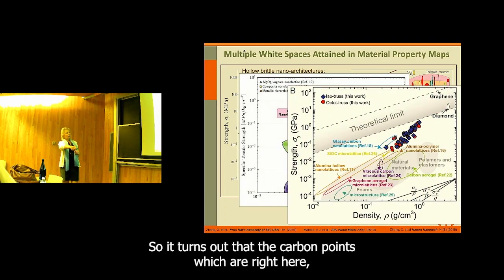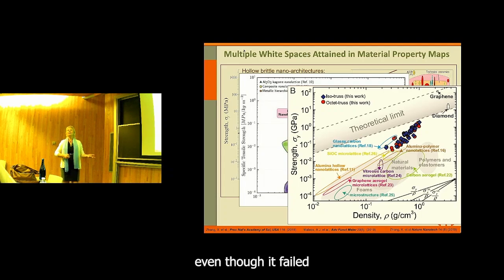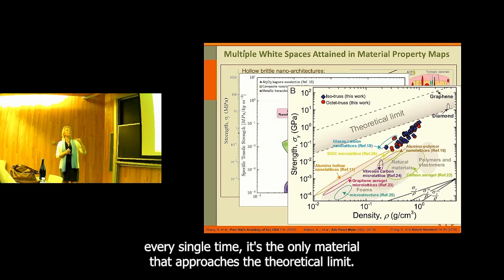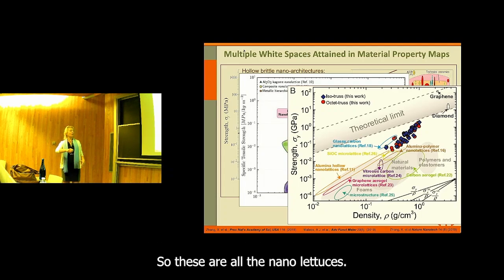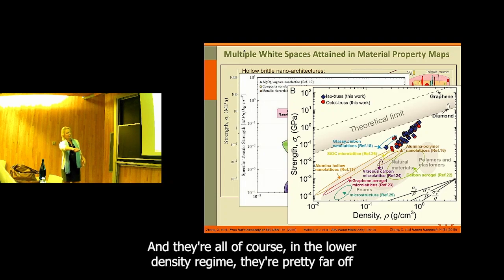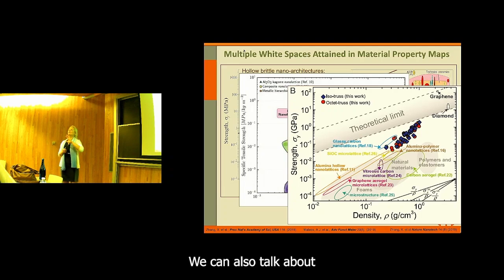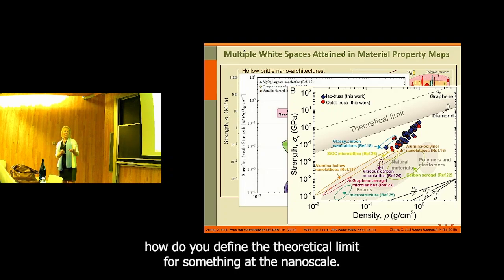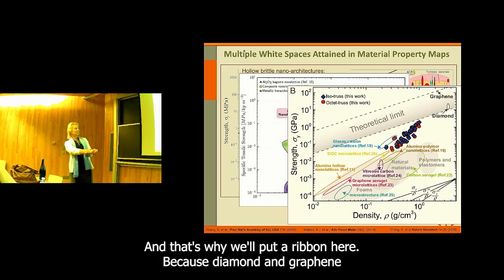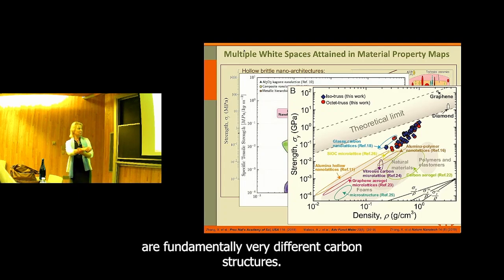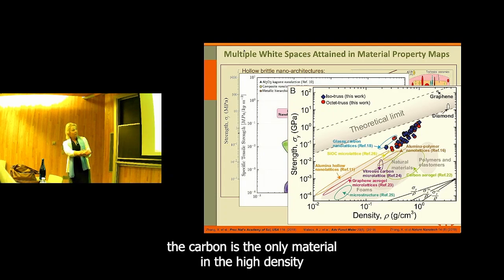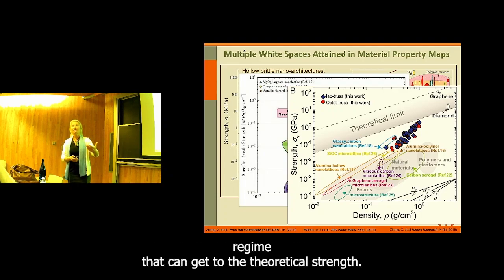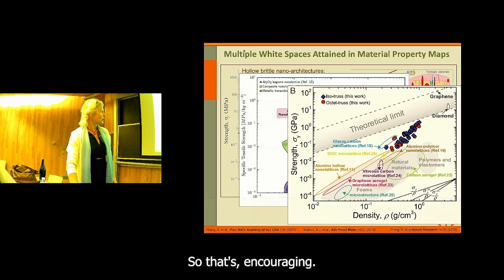So it turns out that the carbon points, which are right here, even though it failed every single time, it's the only material that approaches the theoretical limit. So these are all the nanolattices, and they're all, of course, in the lower density regime. They're pretty far off from the theoretical limit. We can also talk about how you define the theoretical limit for something at the nanoscale, and we can definitely have a discussion about this, and that's why we put a ribbon here, because diamond and graphene are fundamentally very different carbon structures. But nevertheless, the carbon is the only material in the high density regime that can get to the theoretical strength, so that's encouraging.